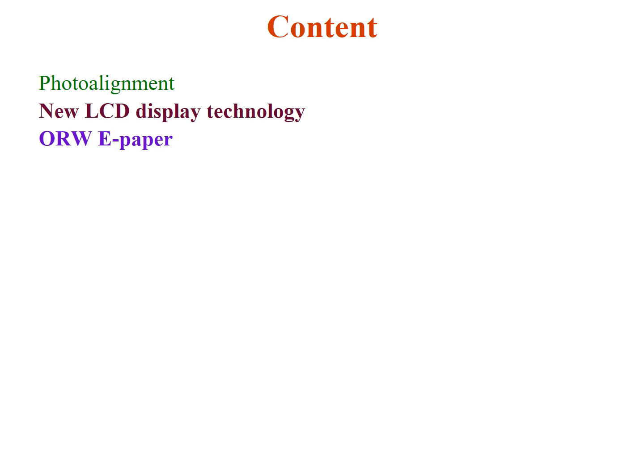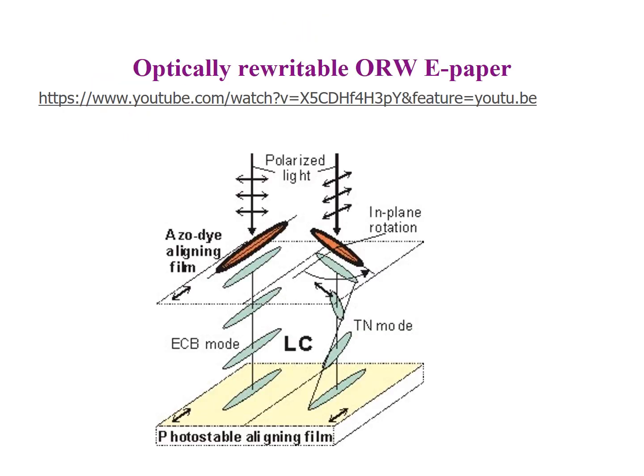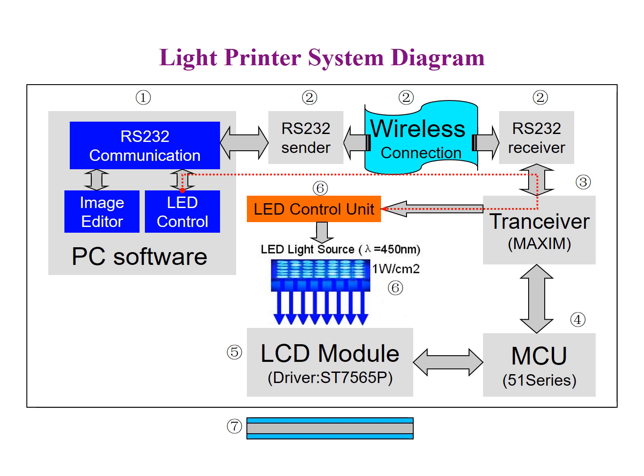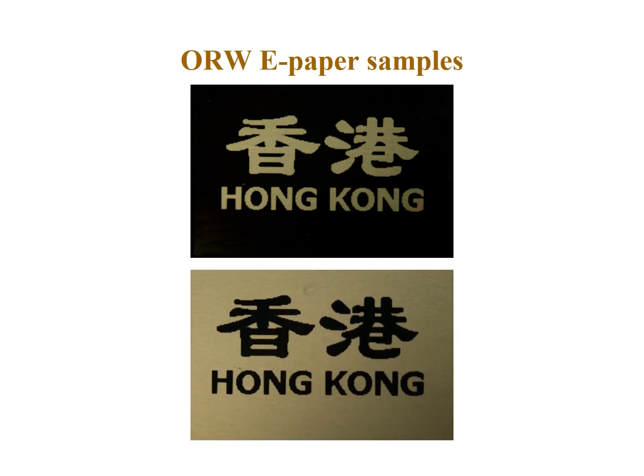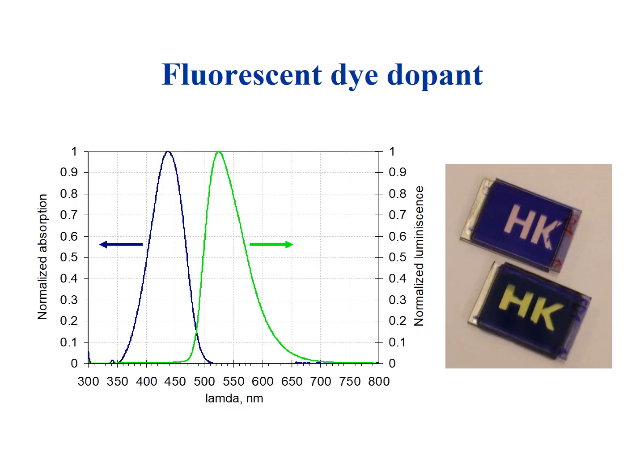Other applications of azo-dye photoalignment technology is optically writable paper, where you actually change the alignment of the azo-dye layer on the surface, and then you change the twist angle of the liquid crystal in the bulk. You put some image on the computer, you transfer it to the LCD module, and then you shine the light and make the image on the liquid crystal layer. We called it a new type of Xerox machine, because Xerox can be done only once, but here you can do the image many times. Depending on the location of the polarizers, you can have white images on a dark background or dark images on a white background.